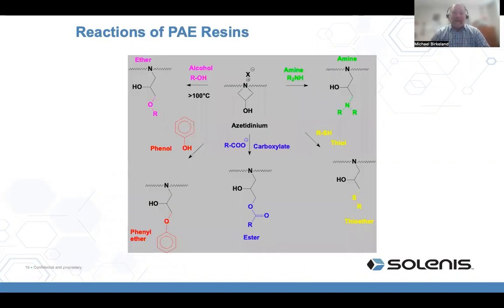So if you're looking and thinking about azetidinium, it will really react with any nucleophile. So alcohols, amines, phenols, carboxylates, thiols, there is reactive ability there. Certainly, each one of those has its own particular kinetics. But if you recall back to the amino acid structure slide, proteins and the amino acids contain all of these nucleophilic chemistries, and that's, I think, why we believe that the PAE molecule and soy are a really good match in terms of making a cross-link adhesive system.